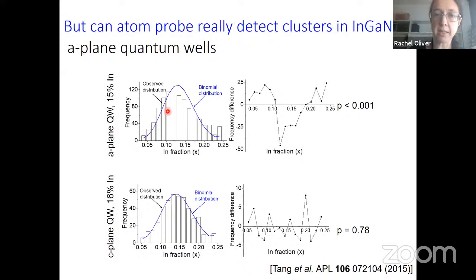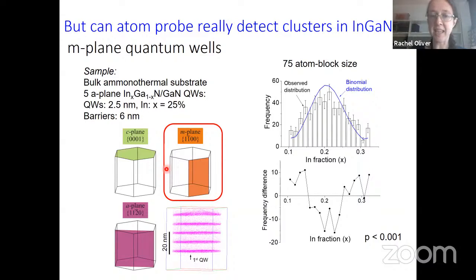Because when we did the statistical analysis and looked at the frequency difference plots, again, we could find that there were lots of regions with too little indium content, lots of regions with too much indium content. And again, these A-plane quantum wells we could show were very, very unlikely to form randomly, that there were real clusters, which in this case we could also pick out nicely with our eyes in the data. We did the same thing for another plane. This is the M plane, the side of my hexagonal prism. And we found exactly the same thing. Too many regions at low indium content, too many regions at high indium content, not enough in the middle, a statistically unlikely distribution for a random alloy.